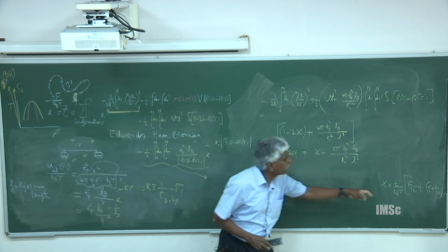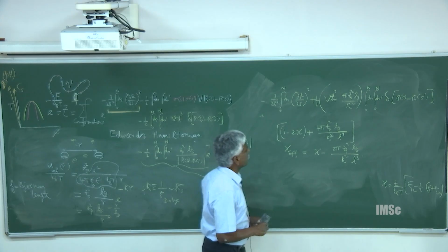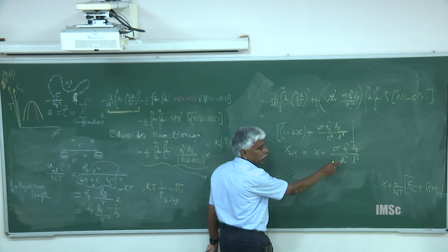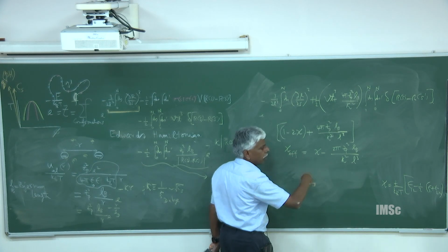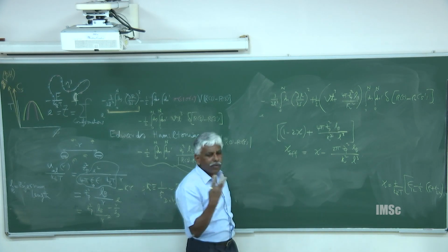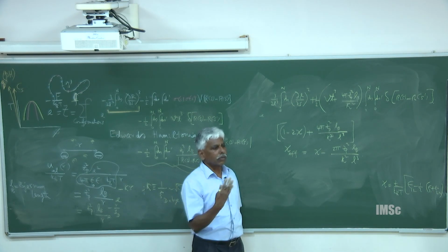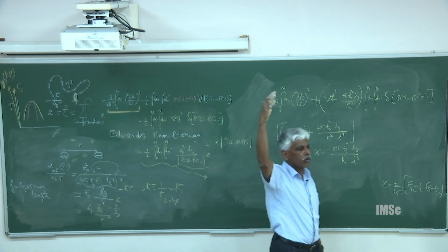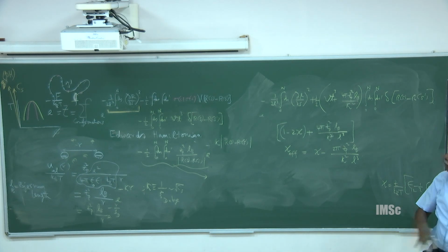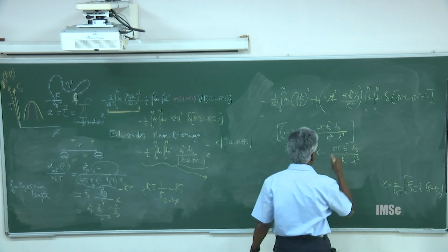Remember, chi is like 1 over temperature. So by adding salt, I am dramatically changing the effective value of chi. You remember in the liquid-liquid phase separation, I told you if chi is sufficiently positive, it will phase separate. So I can adjust the phase diagram with the salt, and Mother Nature does that.